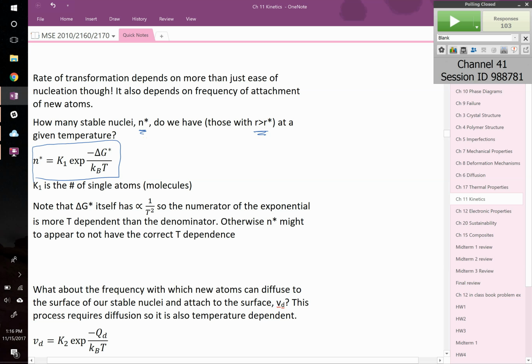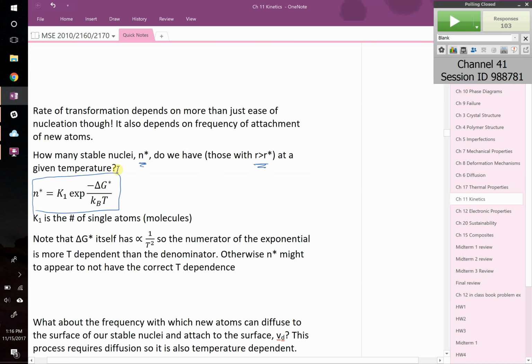It's a thermally activated process, right? You've got a pre-exponential and an exponential. The pre-exponential, we'll just call it K1. That's going to be the number of single atoms that could potentially turn into a nuclei. You multiply that by the exponential of negative activation energy for nucleation formation divided by kBT. So how is this different than every other thermally activated process we've seen so far in this class? What's the key difference? Maybe turn to your neighbor and discuss the key difference here.